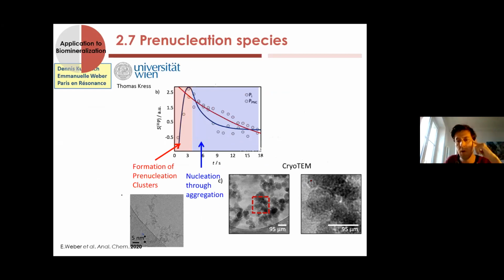You can also run cryo-TEM experiments in parallel just to look at the particles you form. After 6 or 10 seconds, you don't have a crystal yet, but you start to precipitate first an amorphous phase, composed of the aggregation of the previous building blocks. The scale here is not correct, by the way, it's not micrometers, it's nanometers.